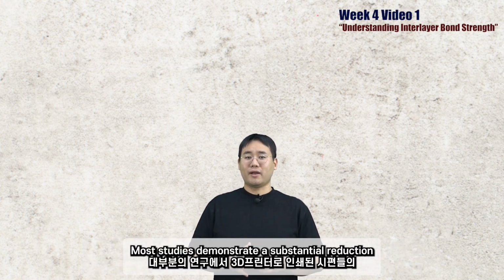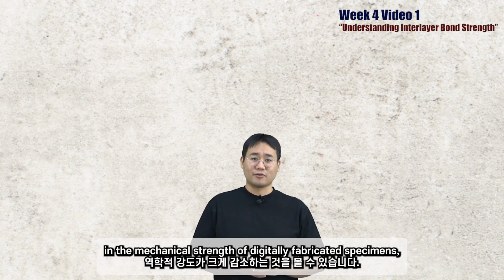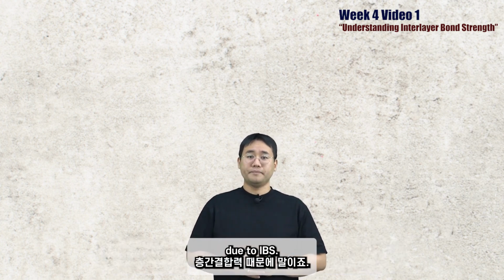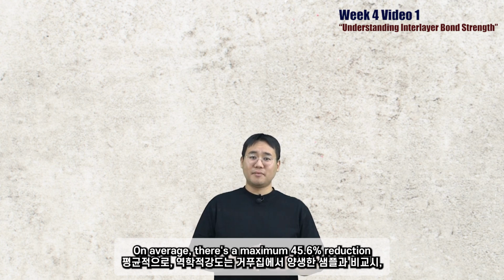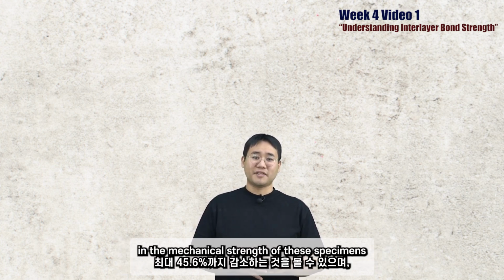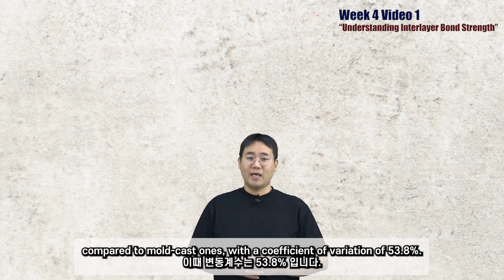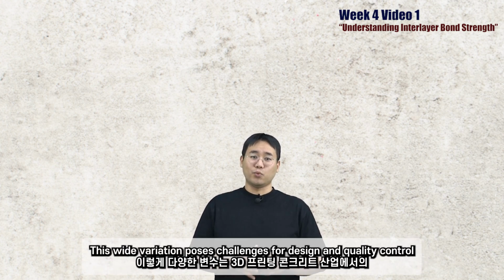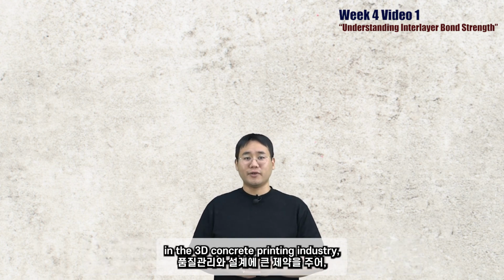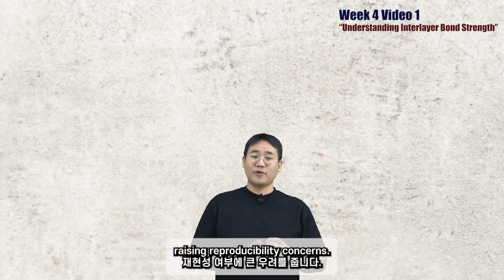Most studies demonstrate a substantial reduction in the mechanical strength of digitally fabricated specimens due to interlayer bonding strength. On average, there is a maximum 45.6% reduction in the mechanical strength of these specimens compared to mold-cast ones, with a coefficient of variation of 53.8%. This wide variation poses challenges for design and quality control in the 3D concrete printing industry, raising reproducibility concerns.